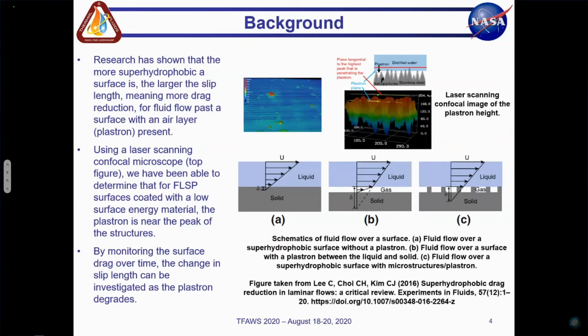Now, Lee, Choi, and Kim, in their review back in 2016, which you can see in this image on the bottom right, talk about how if you just have a hydrophobic surface, as in image A, you get a smaller slip length, and you don't have a vapor layer present. Now, if I go into B, where I have a vapor layer present, I can get the largest slip length possible. One issue with that is that these typically aren't stable themselves without some sort of external work being done. You have seen that done with heating. If you heat to a Leidenfrost state, you can get this vapor layer, or you can inject bubbles.